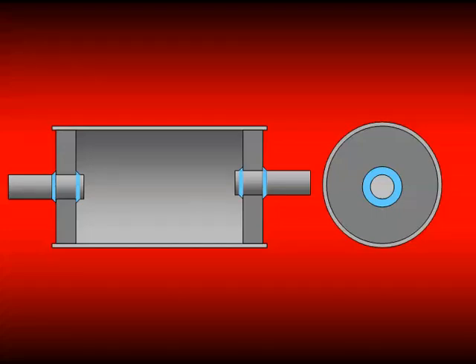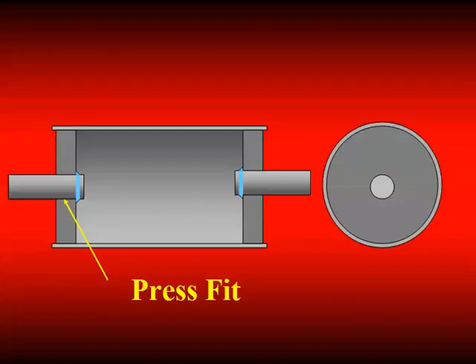And then when they put it into service, they find cracks initiating from the weld toe and going into the shaft. I think you can all see what's going on. They have full reversal loading. The shaft is bending somewhat, and they have a stress concentration at the weld toe, and they crack. The weld's in bending. The solution is go to a press fit, put the fillet weld on the inside, leave the weld off on the outside.